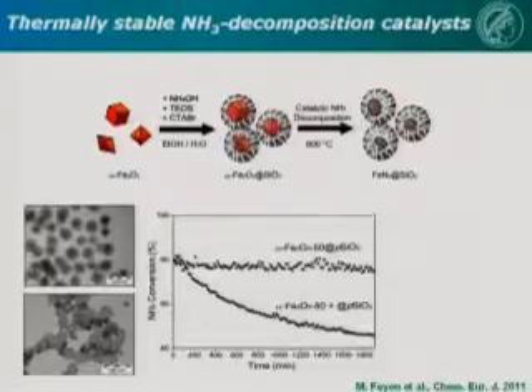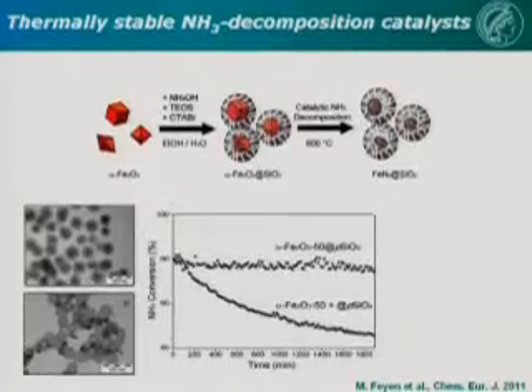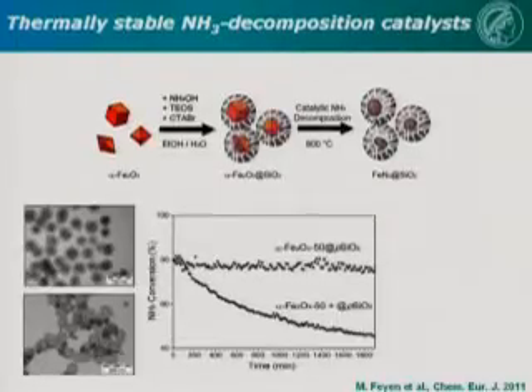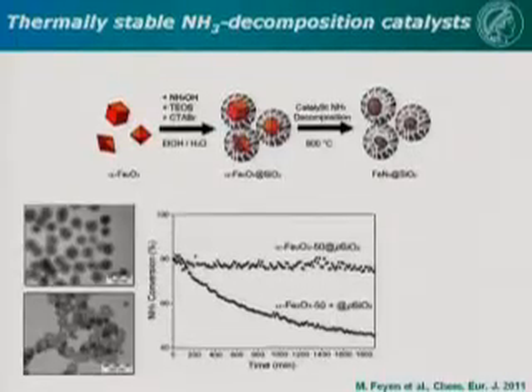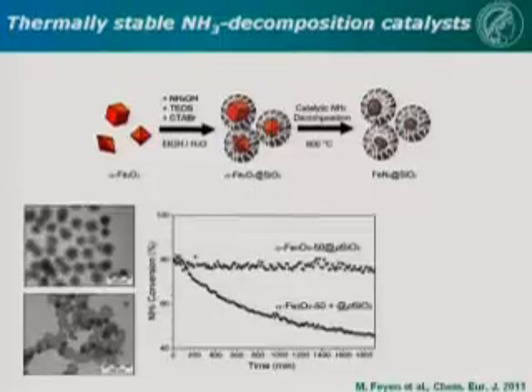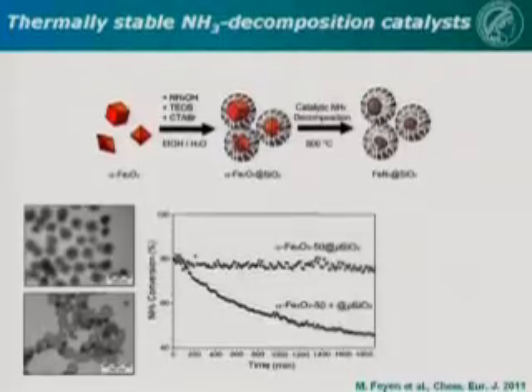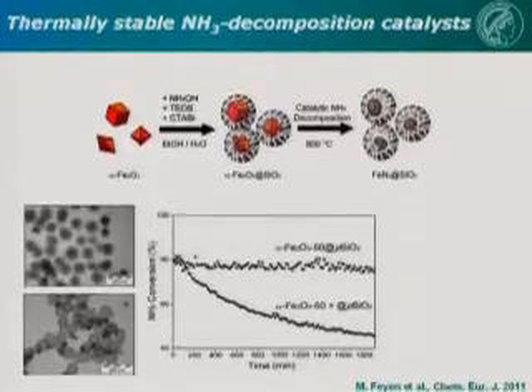And that gave him empty silica shells, and then he added the other half of the iron oxide nanoparticles to this sample. So he had basically an identical sample, one where he had the iron oxide encapsulated, one where he had the iron oxide particles and separate empty capsules.